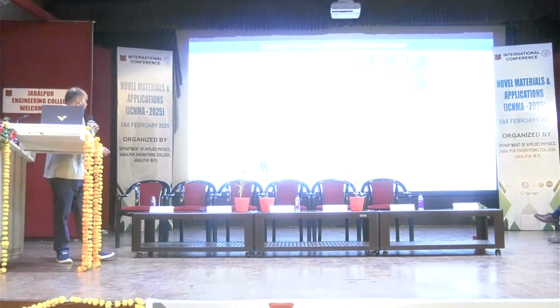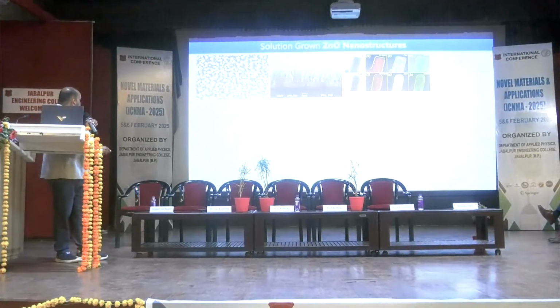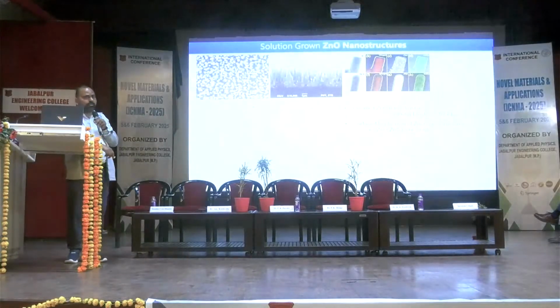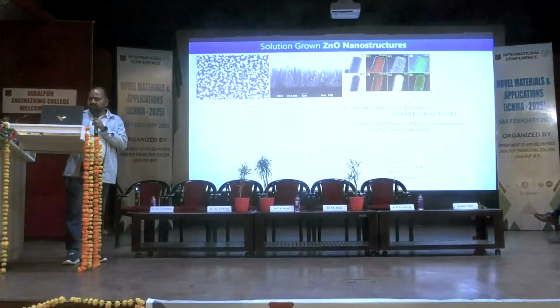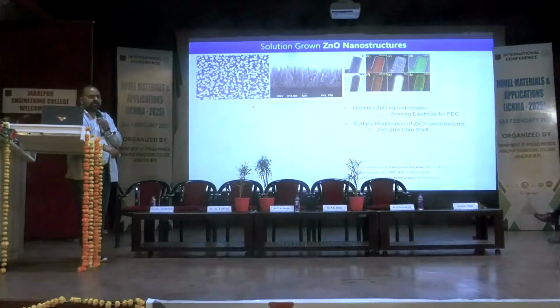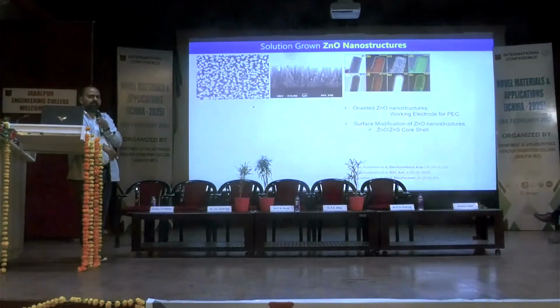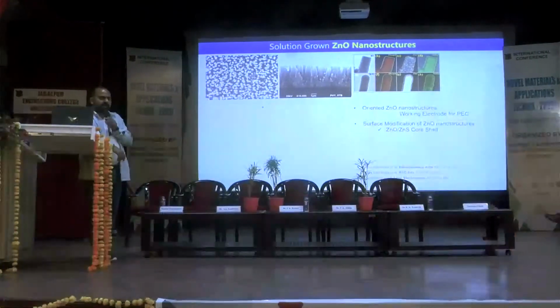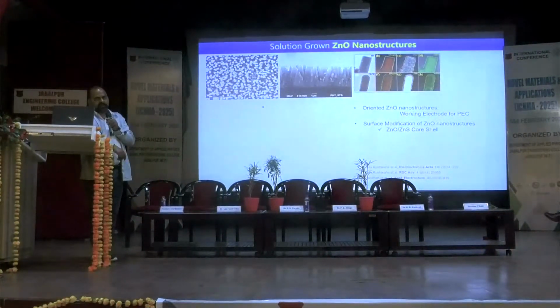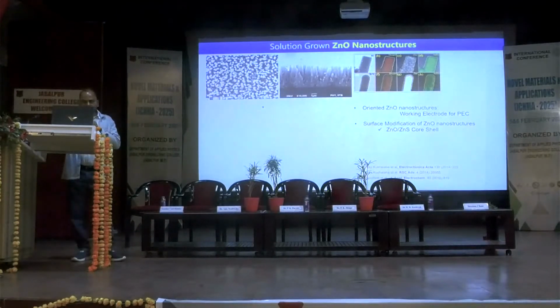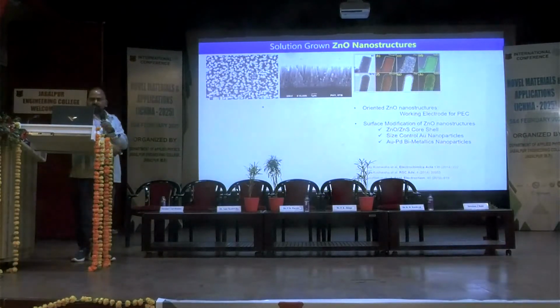The first strategy we adopted was to modify the surface with sulfide. We developed a zinc oxide, zinc sulfide core-shell structure, and we confirmed it by XPS analysis: the surface was just converted into zinc sulfide. The core is zinc oxide, and the core-shell structure helps us in various ways. One is that it reduces the band gap. It also helps us separate the carriers, and it also gives us better stability. Again, we tested these properties, and things were okay.